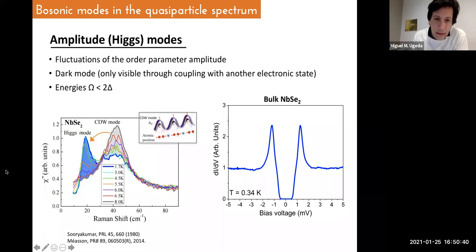In bulk, where these Higgs modes show up so clearly in Raman, these are Raman optical measurements. In STM, they are not seen at all in the quasiparticle density of states. So we don't believe we see it in monolayer. Actually, there should be no reason why there would be replicas of this mode. We actually see four different modes.